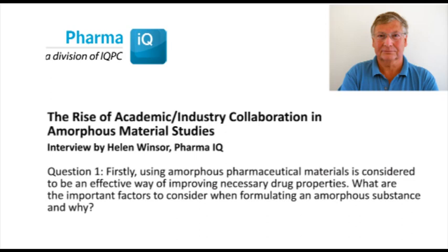So the factors which must be considered are those which have an impact on this stability. The main factor to consider is molecular mobility, because the structure does not change at the glass transition. It is not really a structure problem, but a mobility problem. Glasses are classified according to these mobility properties, and mobility both above and below the glass transition. And the position of the glass transition temperature is a direct signature of the mobility.